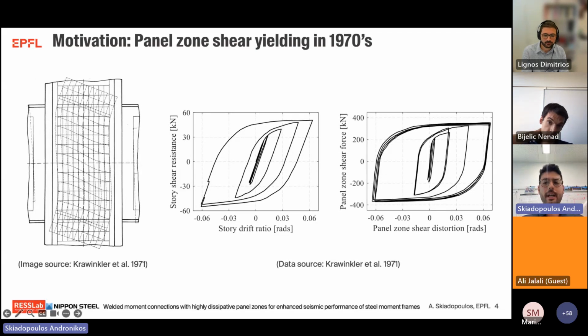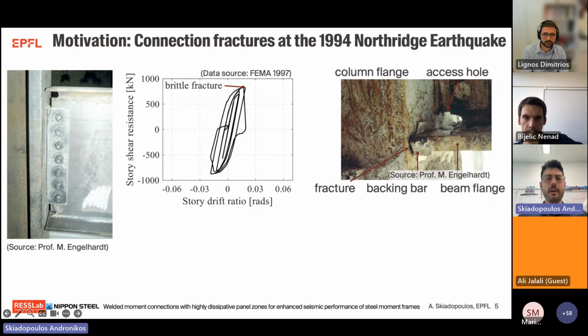However, the main reason why an inelastic panel zone design is not promoted in current pre-qualified connections in the design norms is the increased fracture potential that may be associated with increased panel zone distortions. The increased fracture potential of such a connection methodology was highlighted in the connection fractures of the 1994 Northridge earthquake. As shown in the middle figure, connections at that time were not able to withstand lateral drift demands exceeding 2% story drift ratio, which is equivalent to the design basis earthquake event. So as you can imagine, this is an unacceptable, unanticipated performance. And this unacceptable response is because brittle fractures were identified in almost half of the connections that were inspected at that time, as shown in the far right top figure.